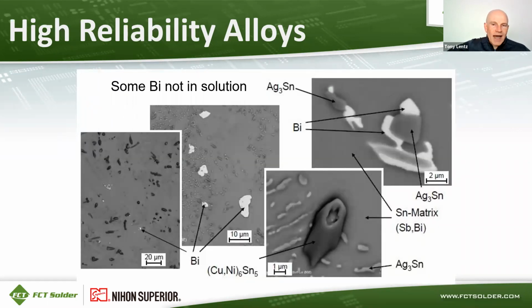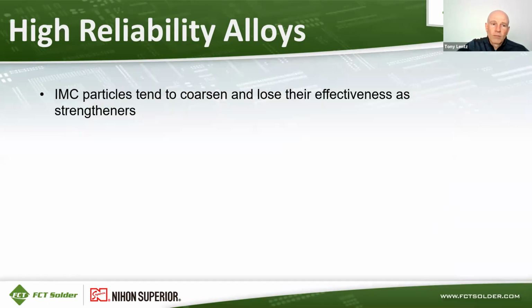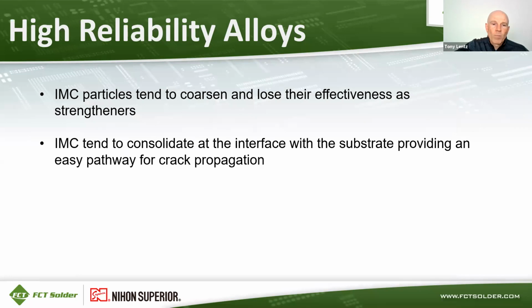But with alloys that contain high levels of bismuth, some of the bismuth does not stay dissolved in the tin matrix. It precipitates out as pure bismuth, like these little islands that are shown on the left. And then in some cases, those bismuth islands might precipitate out on the Ag3Sn particles and agglomerate around them. So these intermetallic compound particles tend to coarsen and they lose effectiveness as strengtheners over time. They also tend to consolidate at the interface with the substrates, providing possible pathways for crack propagation because some intermetallic compounds can be more brittle than the bulk of the solder joint.